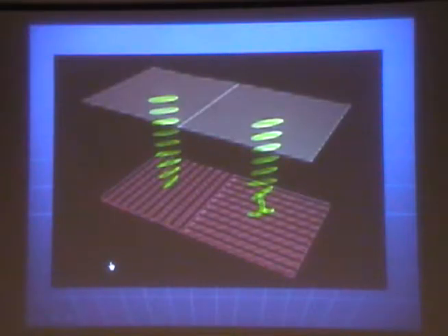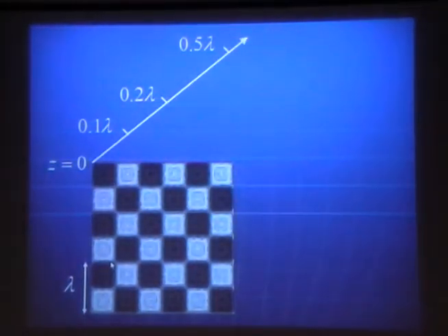If you have just uniform orientation, you can never induce that larger twist angle of more than 90 degrees, so you can never observe the electric field induced buckling transition. But the topological constraint allows us to see this buckling.